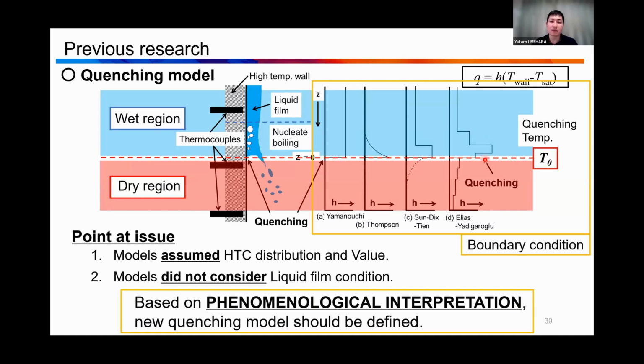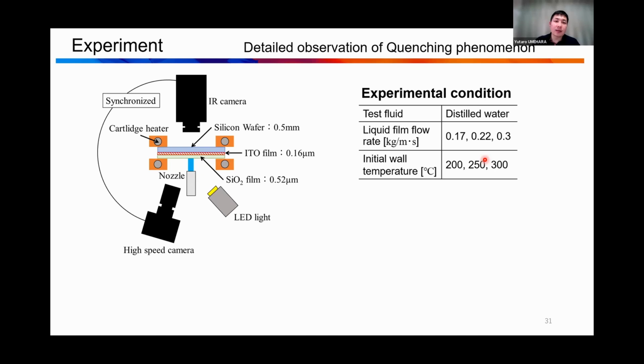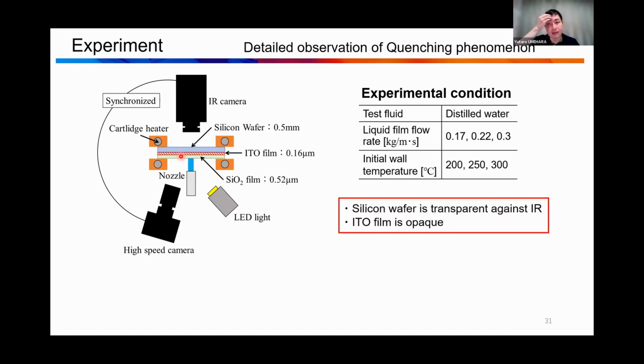Our research motivation is based on phenomenological interpretation. We try to make a new quenching model. That is the objective of my research. We set up an experimental apparatus to measure the actual temperature distribution during the quenching phenomenon by forming the film. We used a silicon wafer as a high temperature wall, and then an oxide film was added. Because the silicon wafer is transparent against infrared light, and the oxide film is opaque against the IR, we set the infrared camera on the back side, and we can directly see the temperature distribution here.